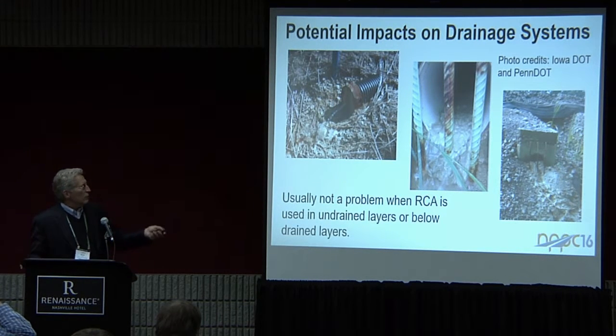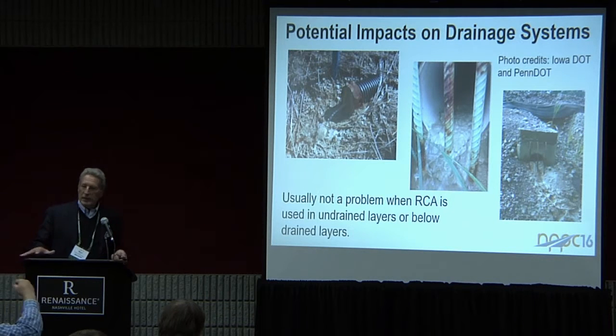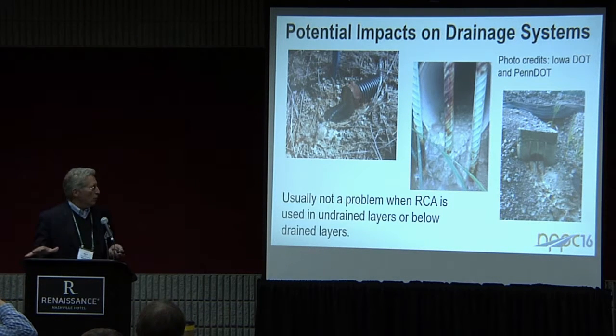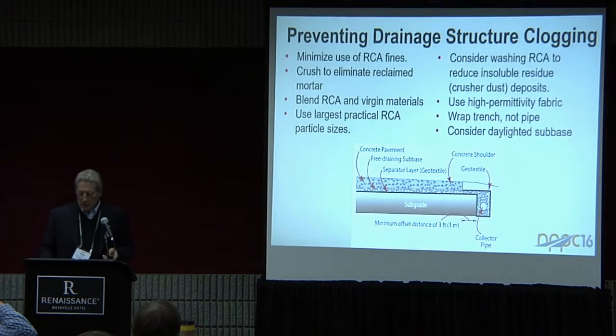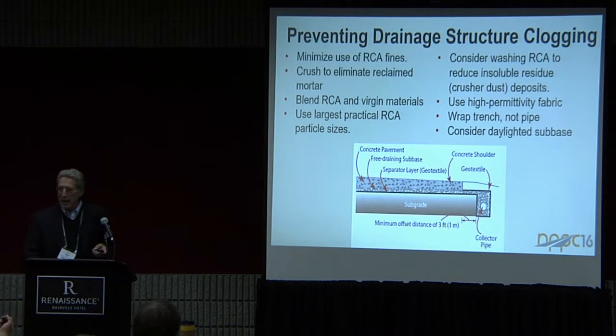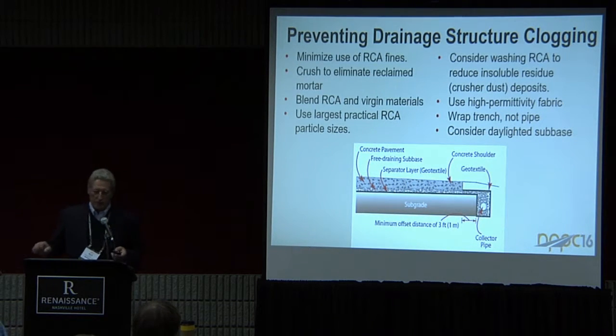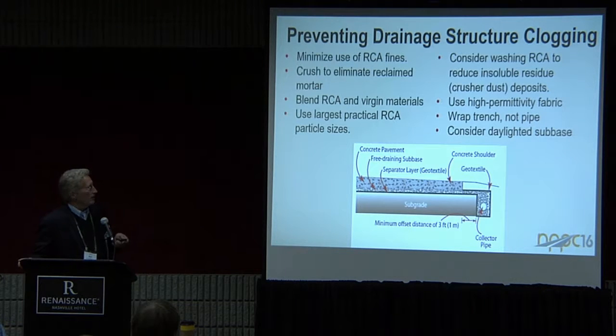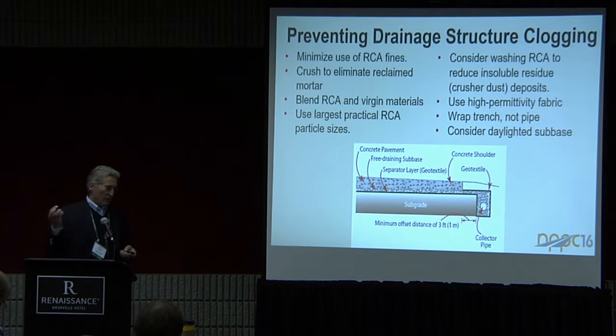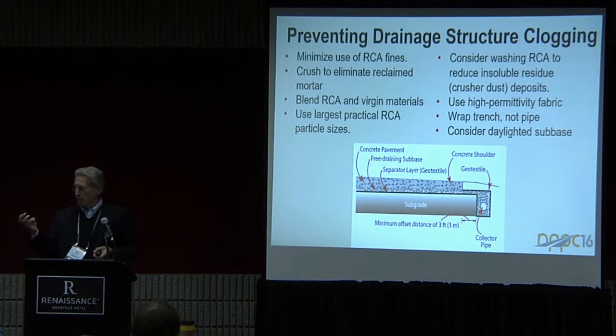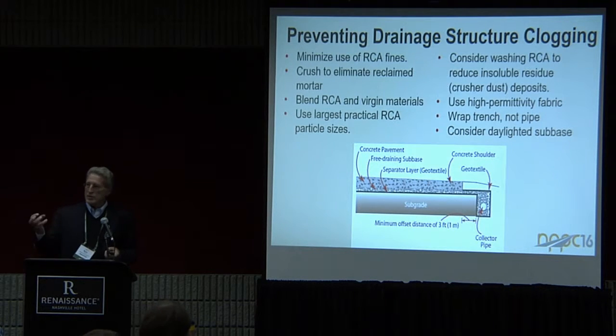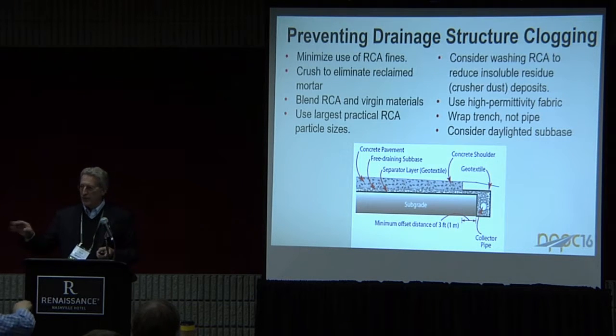So as long as we use the recycled concrete in an undrained layer or below the drained layers, we don't have a problem at all. But there are also techniques for preventing that from happening when we're using it in a layer that is drained. There are a lot of different approaches here that have different degrees of efficiency. First of all, minimizing the use of the fines reduces the surface area that you can run water over, and you reduce this kind of a problem. You're not dissolving as much dust and calcium hydroxide out of those particles. So get rid of the fines.